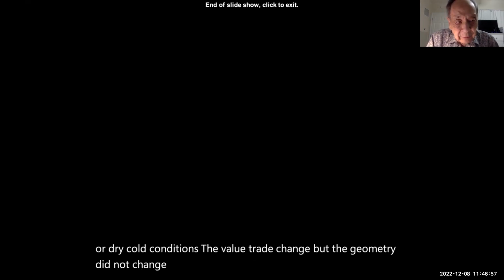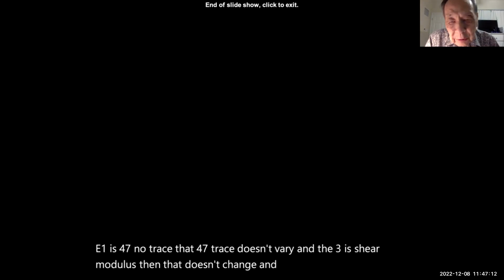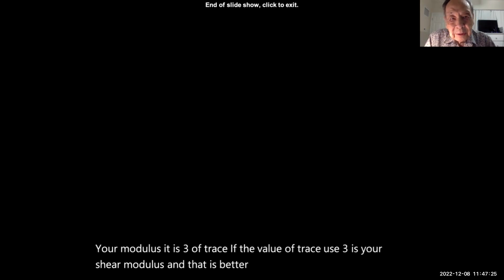In other words, if you have a 0/90 laminate, the E1 is 47% of trace. That 47% of trace doesn't vary, and the 3% is shear modulus, and that doesn't change. And the advantage is you don't really need to measure shear modulus. It is 3% of trace. If you know the value of trace, your 3% is your shear modulus, and that is better than you can measure because shear modulus is so difficult. It has a nonlinearity, and the test method is really very complicated. So you can make much simpler conditions.